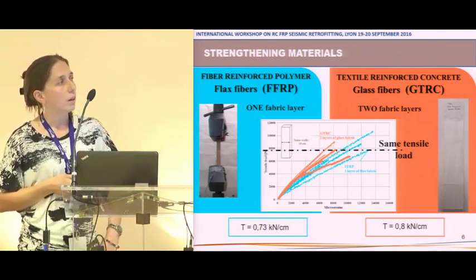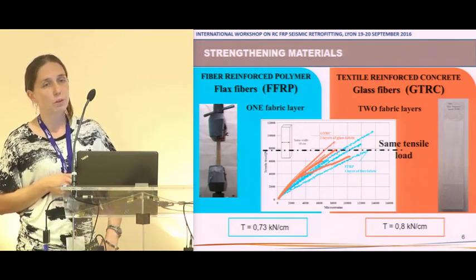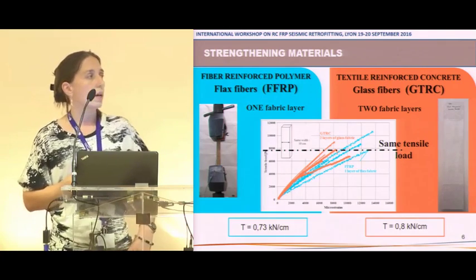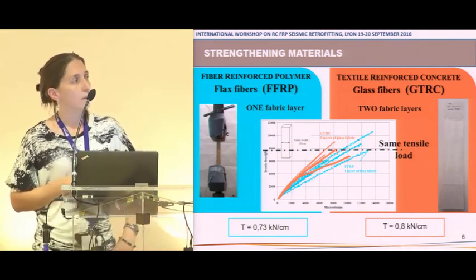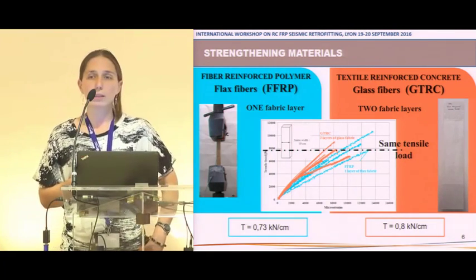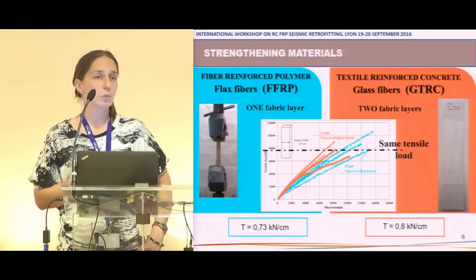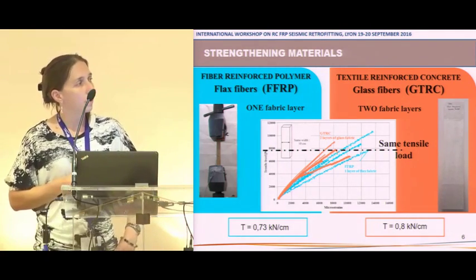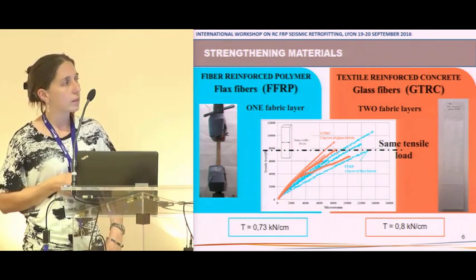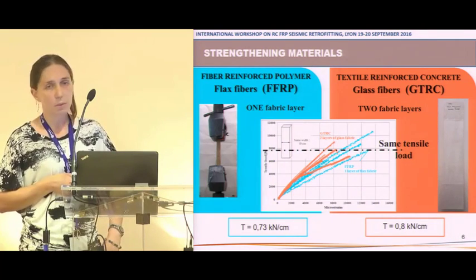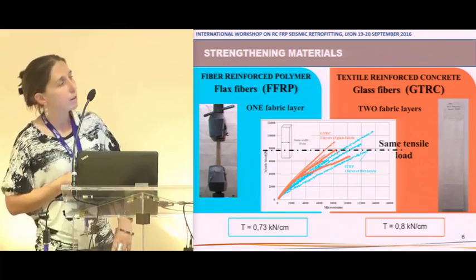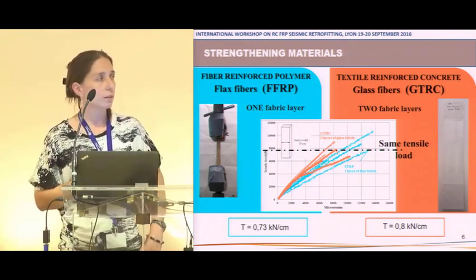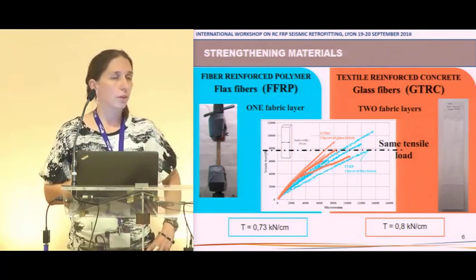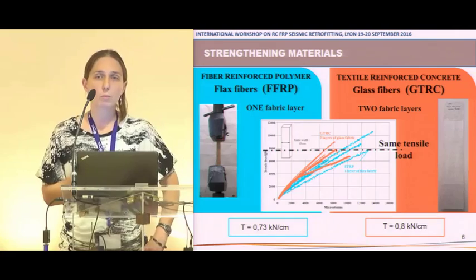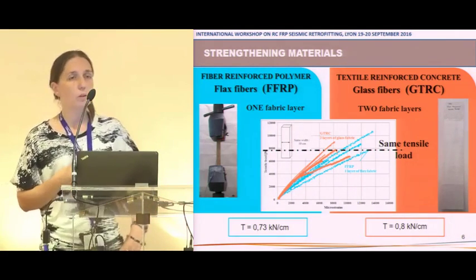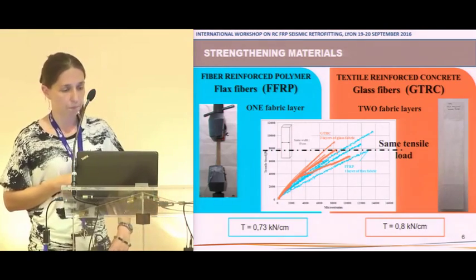with glass fabrics. In fact, the number of fabric layers has been chosen in order to have the same tensile load, and it has been checked by performing direct tensile tests on composite samples which have been realized when the walls have been reinforced. And we can see that FRP with one fabric layer and TRC with two fabric layers give the same tensile load, that is about 8,000 newton if we take a width of 10 centimeters. It is important to note that the thicknesses of the composites are really different, because TRC are 3 or 4 times as thick as FRP.